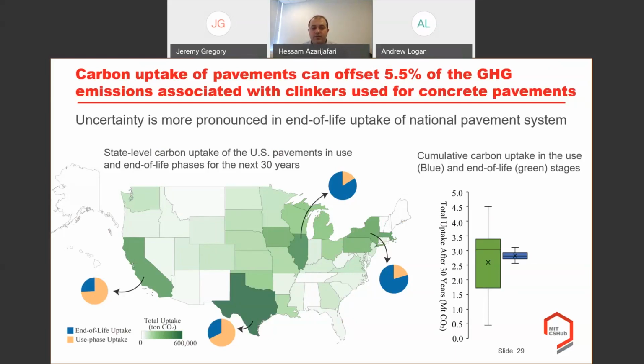Once we sum up all the results here for concrete uptake during the use phase and end of life, we will reach this whisker plot chart. For the use phase, the blue one, and the end of life, the green one, the median value of the carbon uptake is very close to each other. So we can assume that the amount of carbon uptake in the concrete pavement network in the United States at the end of life and at the use phase is very similar to each other. However, we can see the uncertainty related to the calculation of the end-of-life uptake is quite huge compared to the use phase, and that's because of the geometry of the stockpile that we have.